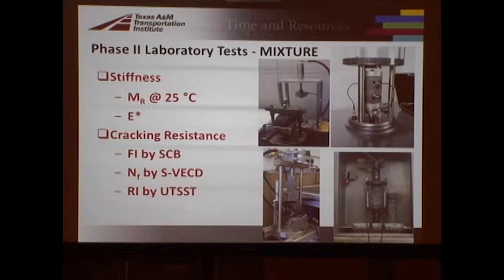We're also doing fatigue life by the simplified viscoelastic continuum damage test, and we're also doing the resistance index by the UTSST test. All that is a better, improved TSRST test, which was the thermal stress restrained specimen test. It has more analysis, and it measures the strain in the specimen that's not restrained also, an unrestrained specimen. So it's just an improved thermal cracking resistance test. So we have 2 cracking resistance tests at intermediate temperatures and 1 at low temperatures.